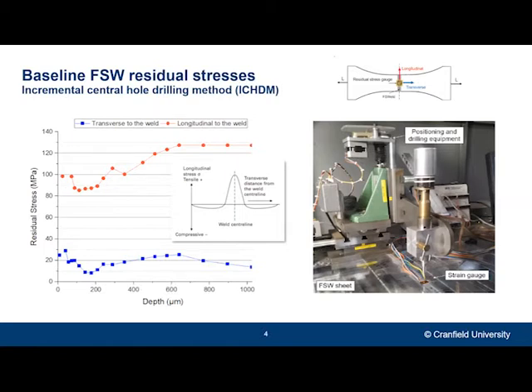However, for this particular project, the transverse direction of the welds is the most relevant because it coincides with the loading direction of the fatigue specimens that I'm using. Luckily, these stresses are almost negligible, as you can see in blue. This is due to the fact that the variation in temperature in this direction is very small when you compare it to the longitudinal direction, which is also the traveling direction of the tool.